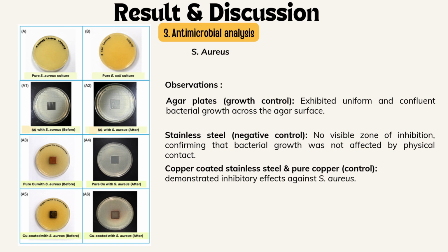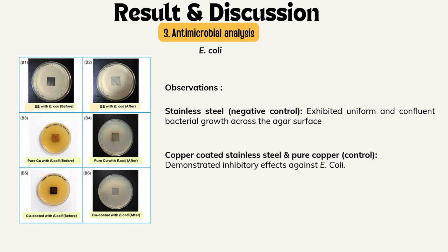The results show that the copper-coated stainless steel sample has relatively the same inhibitory effects against S. aureus as the pure copper does. Next, for the antimicrobial analysis of E. coli, it is the same case for copper-coated stainless steel, which showed relative similarity of inhibitory effects against E. coli as the pure copper does.